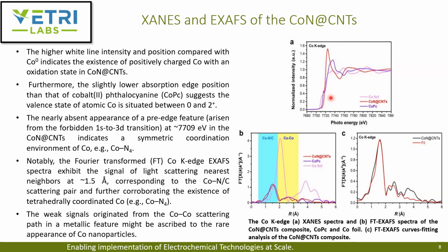And as we can see in this region, the pre-edge feature is absent. There is no presence of the pre-edge feature that could arise from the transition of 1s to 3d at 7709 eV, which indicates that there is a symmetric coordination, that is, the Co with 4 nitrogen atoms.